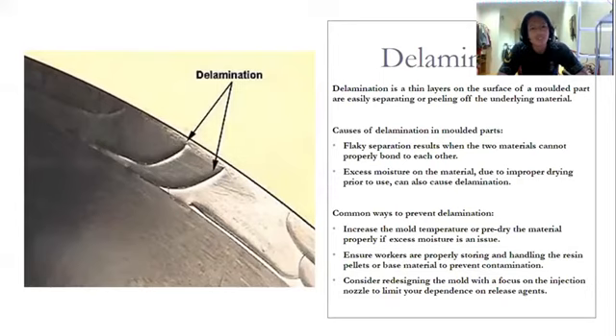Next is delamination, which is a thin layer on the surface of the molded part that easily separates or peels off the underlying material. The cause of the delamination is flaky separation that results when two materials cannot properly bond to each other. Excess moisture on the material due to improper drying prior to use can also cause delamination.